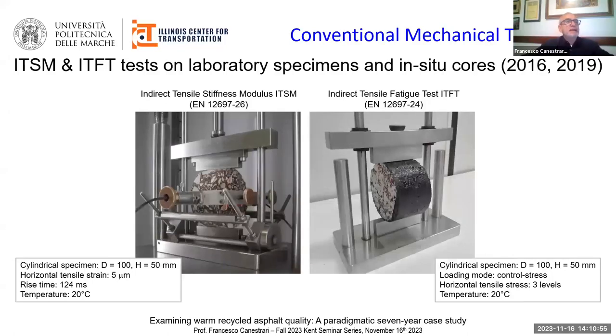During the construction of the trial section, the loose mixtures produced at the asphalt plant were taken and immediately compacted in the laboratory with the target number of gyrations. Then, conventional mechanical testing in terms of indirect tensile stiffness modulus and indirect tensile fatigue tests were carried out according to European standards on both laboratory compacted specimens and in situ cores immediately after the construction of the trial section in 2016 and also 3 years later in 2019.